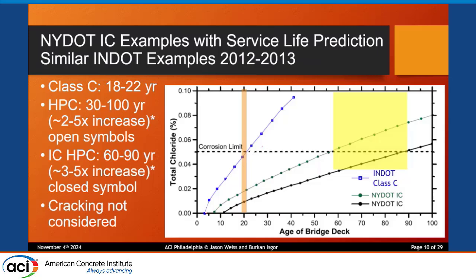When you couple together the fact that you have cracking, this moves way over here, and you start that corrosion process much earlier on. Many DOTs are replacing bridge decks much more rapidly than they need to because they're corroding the reinforcing steel, right? And they're having to get out there and replace these. In the cases where we have internal curing, we have substantially increased the time to corrosion, plus we've reduced or eliminated that cracking potential. So now we're doubling or tripling the service life of the concrete.